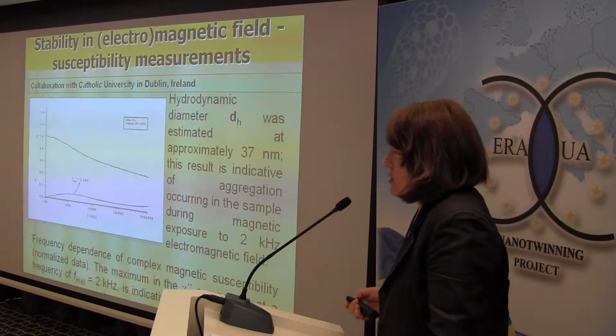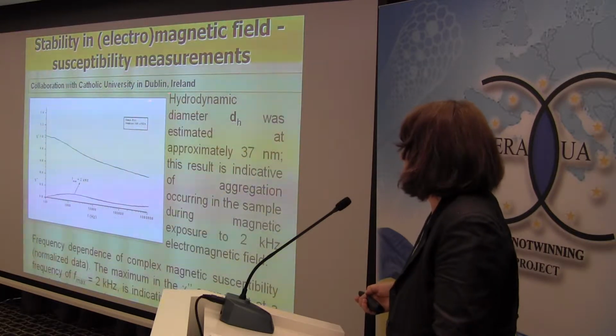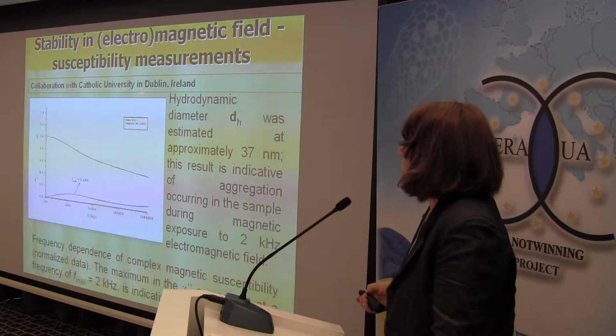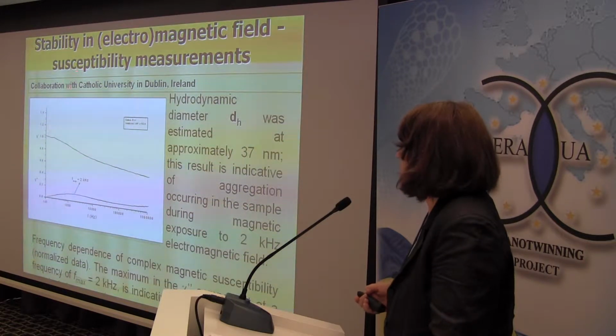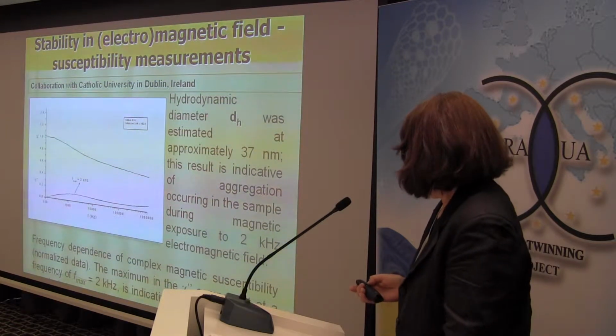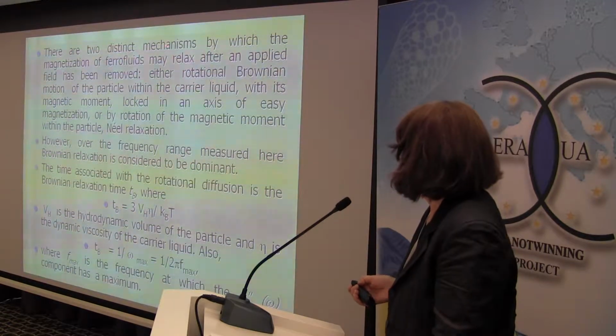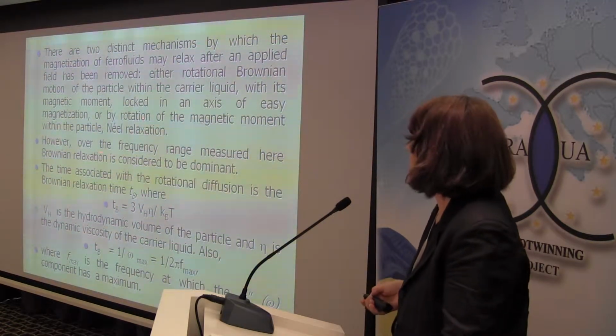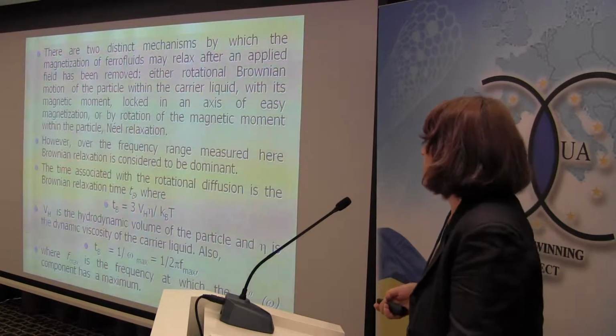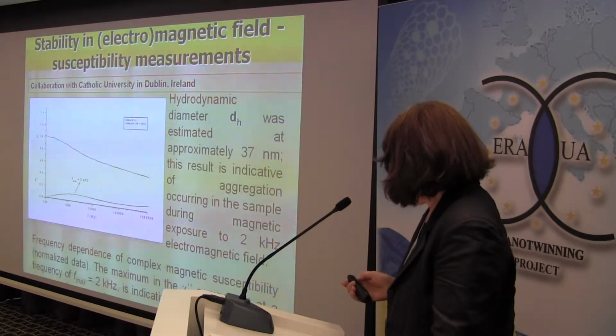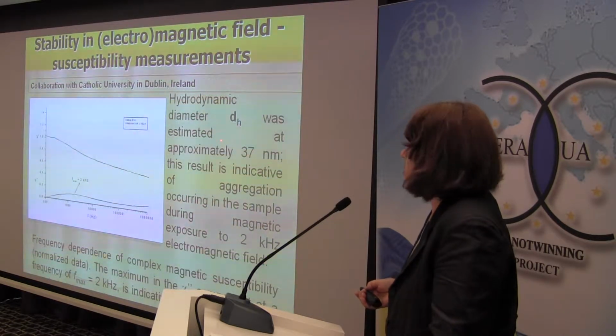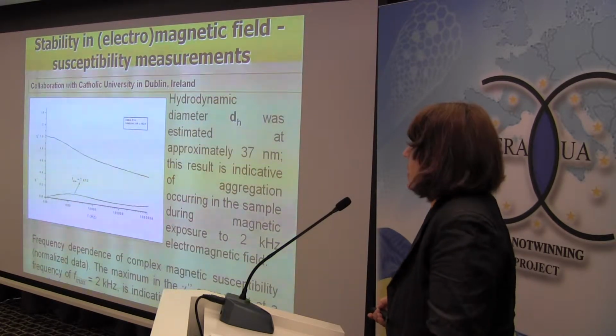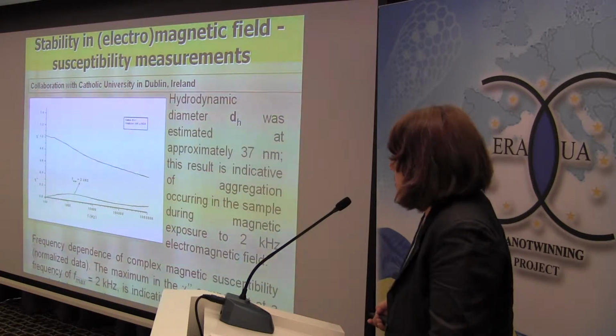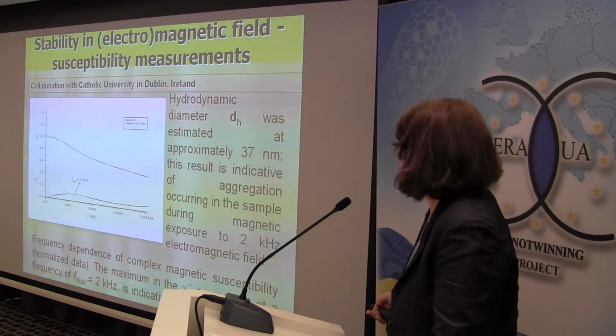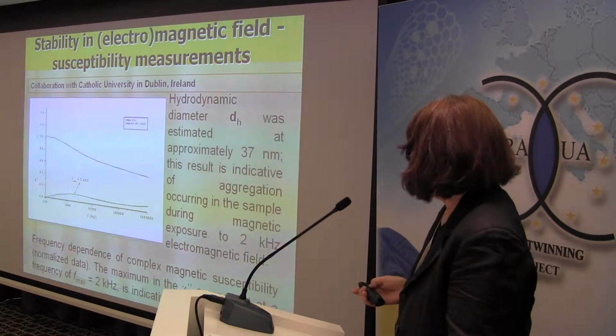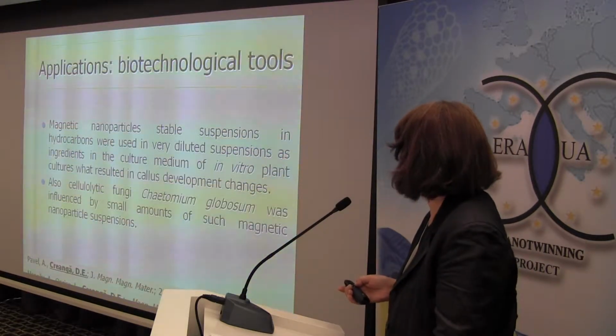Other studies that we began to do in collaboration with Dublin, Ireland, Catholic University concern the complex susceptibility, and the first results show that according to the theory of magnetic relaxation, Néel relaxation versus Brownian, one could lead to the hydrodynamic diameter of the aggregates that are formed when the critical frequency value is about 2 kilohertz. So the hydrodynamic diameter is no higher than 37 nanometers.